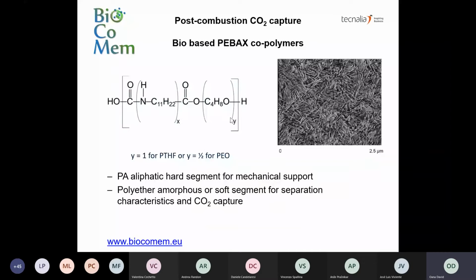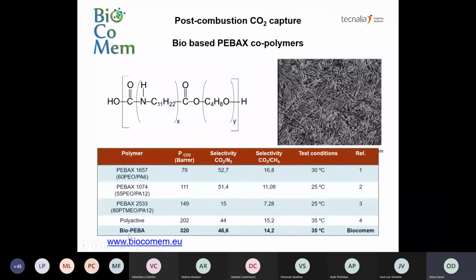So in BioCoMem, on one side, we will make hollow fiber membranes by dip coating, and on the other side, we will change the chemistry of polyamide and polyether block in order to make them spinnable into monolithic hollow fiber membranes. And here, the starting point will be a new PEBA type polymer that is made from polyamide 11, this bio-PEBA that is from bio-based building blocks. It has very good gas permeation properties, much better than any of the polymers studied so far. So this is a new polymer from Arkema.